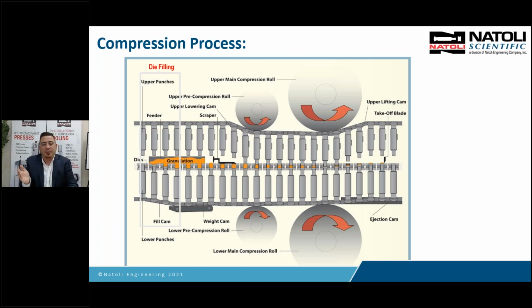Where if your fill cam is positioned properly underneath the feeder, it will pull down and suck powder in with that partial vacuum. If you do have a machine out there that has this design where you're not pulling in powder at the fill cam, Natoli has a solution for you. It's called a fast track. We'll basically custom design your fill cam for your press so it does pull down underneath the feeder. This might be a common reason why you're having weight variations at high speed on your tablet presses, because this fill cam needs to be positioned underneath the feeder.